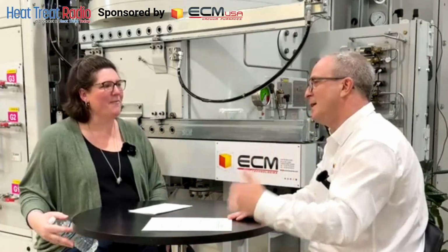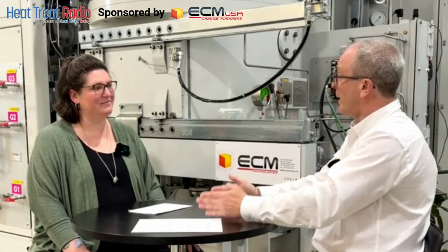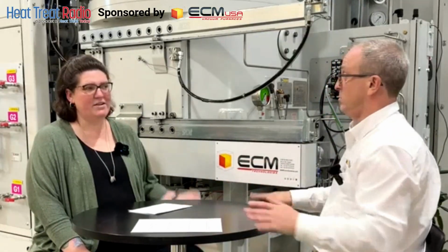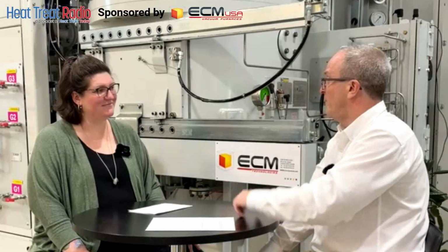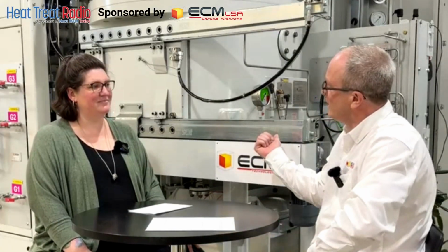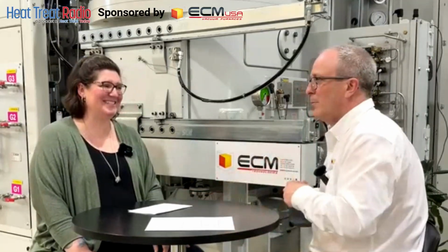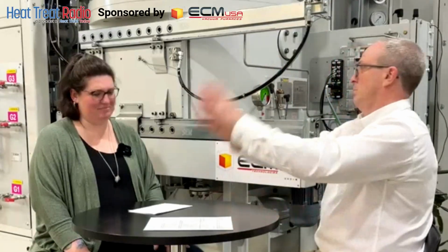And then you have to heat up and to quench. So in a straight heat treatment, it's heat up, be sure you're at temperature, you carburize, and you quench. One test, pretty much. I do a lot of one tests. A customer asked me to run a test for a flex system, a larger system. I do it here first because it's cheaper for me. I've got the slab, and I mixed a different part, different design, and run. Oh, it's an 8620. Sure, let's go. And usually it's good.